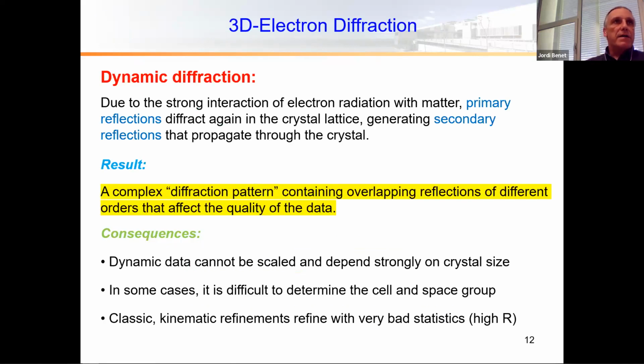Evaluating these, I see that electron diffraction is an effect in which primary reflections diffract again in the crystal lattice. So we get secondary reflections which propagate through the crystal. This results in a quite complex diffraction pattern with overlapping reflections of the different orders of diffraction. The consequence is that we have what we call dynamic data, which cannot be scaled and is strongly dependent on crystal size. In some cases, due to these modified intensities, it's difficult to determine the unit cell and the space group. And when we use the classic kinematic refinements, we get very bad statistics. We get very high R values, which at the beginning made me think, wow, what is this? But they seem to be normal when using electron diffraction.